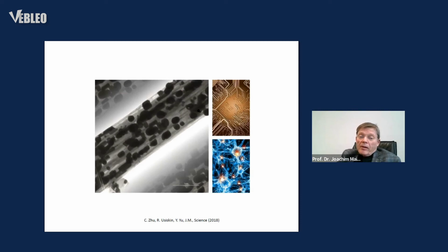But they are electrochemically not separated. They are connected because the electrons go along with carbon, and the ions come from the electrolyte here and do not have a big distance to travel. The whole carbon tube collects these kinds of particles, so you don't need a binder. It's, in a certain sense, a perfect electrode structure.